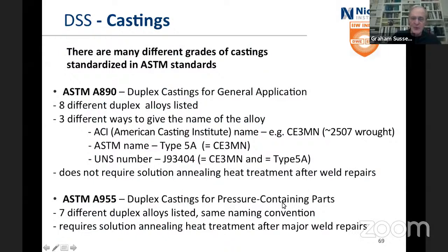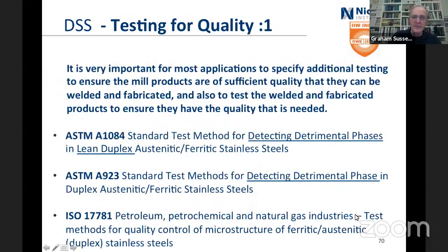A955, duplex for pressure containing parts, 7 alloys, same naming conventions, but it's pressure containing parts, so it requires solution annealing after major weld repairs, just to make sure that the hardness is okay and the microstructure is okay. And for testing for quality, this is not just for welded materials, this is for stuff actually arriving.